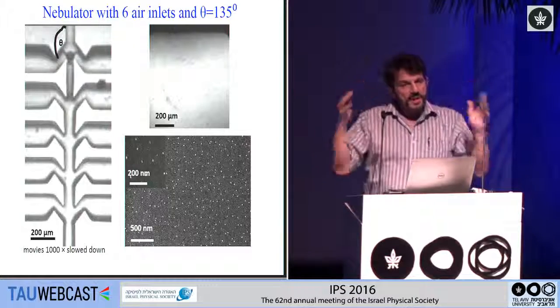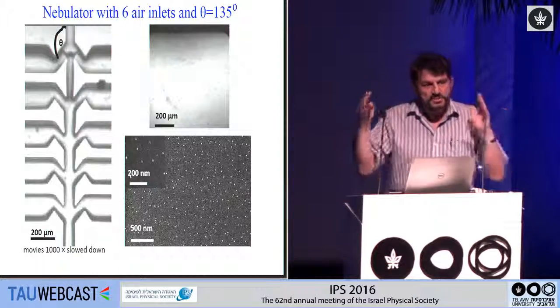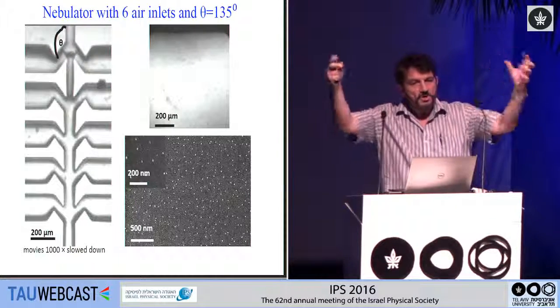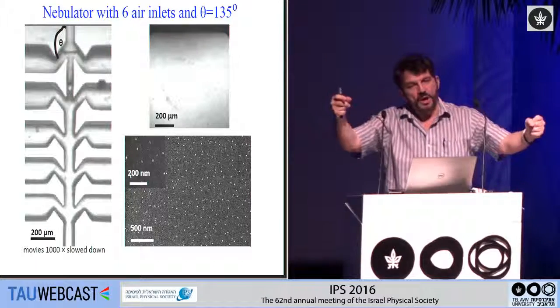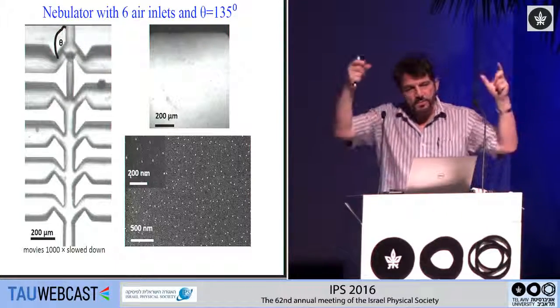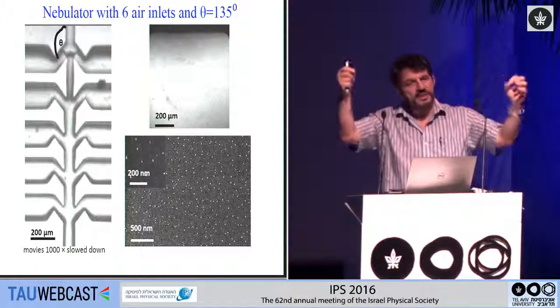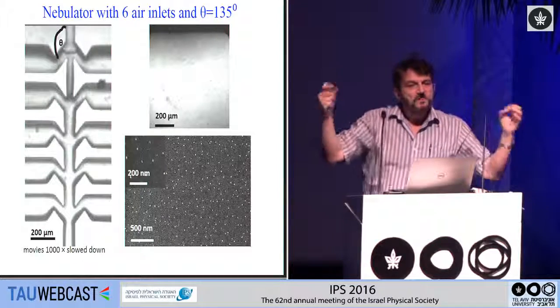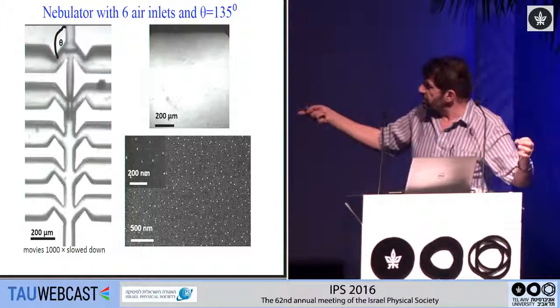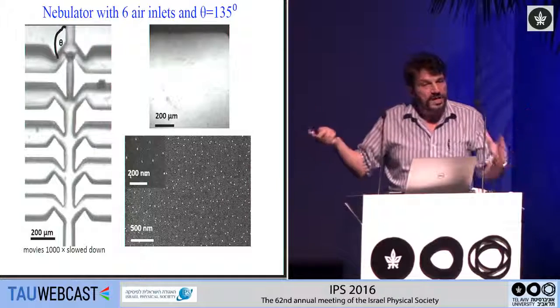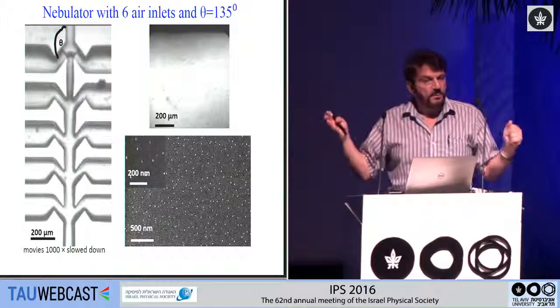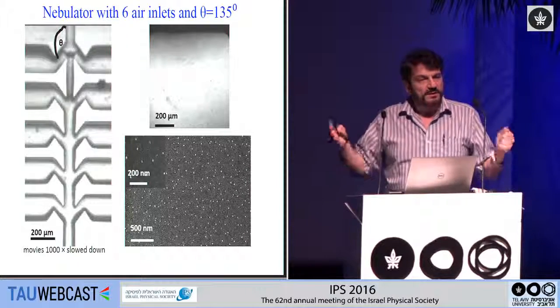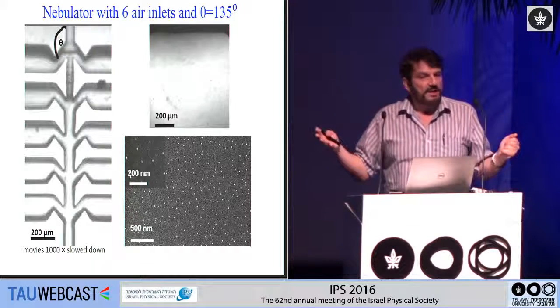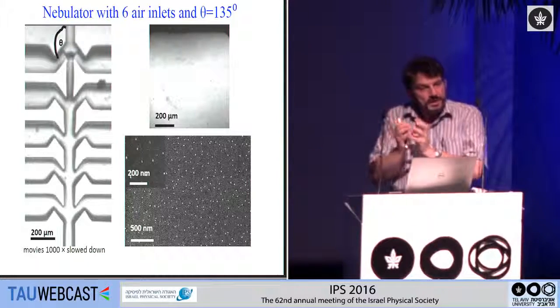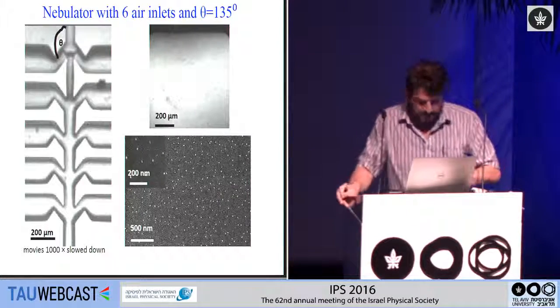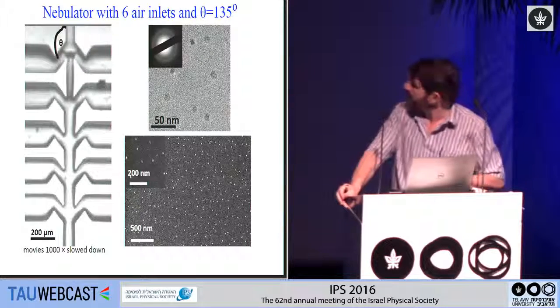So the way you have to understand this is that you're tearing apart this drop. You're tearing it into much smaller drops. We call this a nebulizer. We nebulize the drop. We break it into tiny drops, and the measure of the size of the drop is just given by the particles that you produce. So here's a very, very simple way of producing nanoparticles by nebulizing the fluid, by first breaking it into a big drop and then breaking the big drop into much smaller drops.